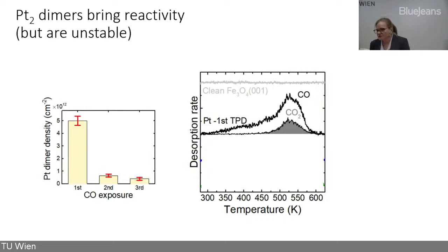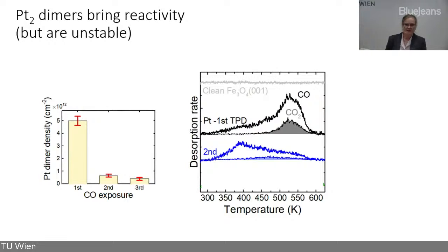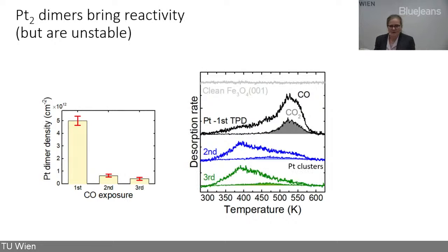Unfortunately, it's a really lousy catalyst, because if you put CO there and run it once, CO2 comes off, but if you do it a second time, the platinum dimers will have the CO desorb at a lower temperature, and there's almost no carbon dioxide anymore. The reason is that there are fewer of these platinum dimers, they have balled up and become bigger clusters, and these clusters are less reactive for CO2 oxidation for two reasons.